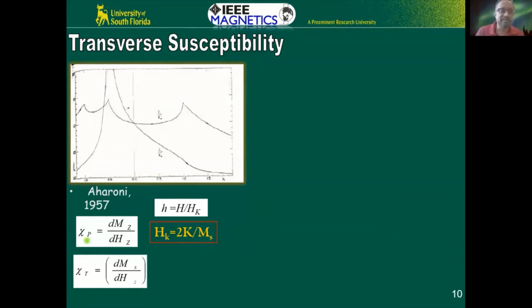What he plotted here is that he analytically calculated both the parallel component and the transverse component of susceptibility. You can see that the parallel component is the conventional one, dM by dH in the same direction. But when you apply fields in the crossed field direction, the transverse direction, this is the transverse susceptibility, and you see that it's a tensor. That's what we are trying to measure.